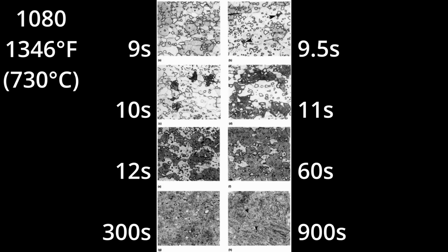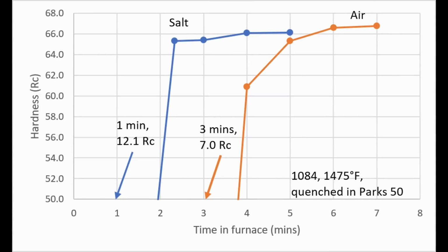And then it needed another several minutes to be able to dissolve most of the carbide. So 10 minutes were required to dissolve most of the carbide after the 5 minutes was already done. So again, some knife makers forget that we're not just heating up the steel, we are waiting for certain things to happen. But we were able to see the difference in this case between the air furnace and the salt furnace, the salt several minutes faster to heat up the steel.